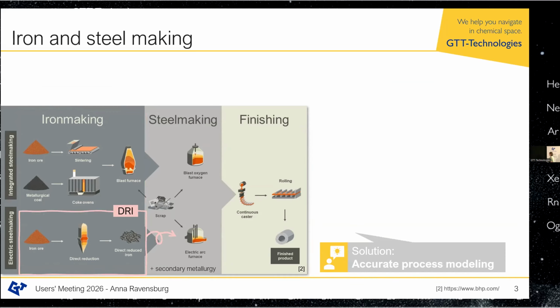There are two different routes that I'm showing here, the blast furnace route and the DRI route. The DRI route is really promising because there is the potential of reducing the CO2 emissions of the blast furnace route by 97%. In the DRI route you have porous pellets, and you reduce them with CO in very traditional ways. You can, however, replace this with H2 and do hydrogen reduction. In pure hydrogen reduction, you could save up to 97% of the CO2 emissions of the blast furnace route. So this is why we are focusing on this, because it's a very promising candidate to decarbonize the steel industry.